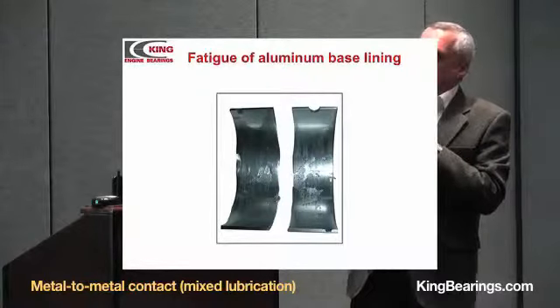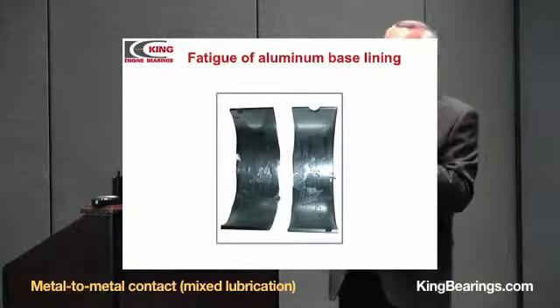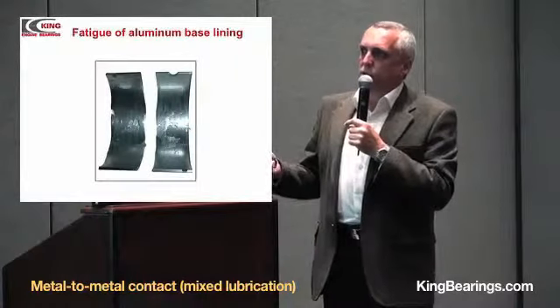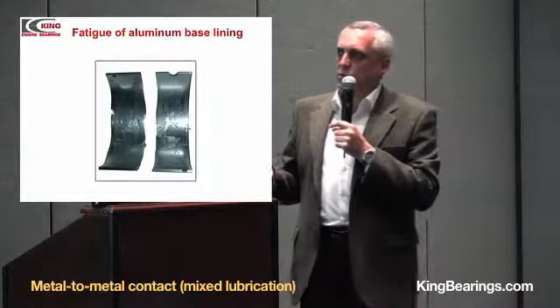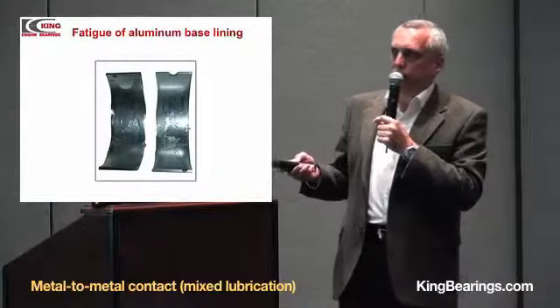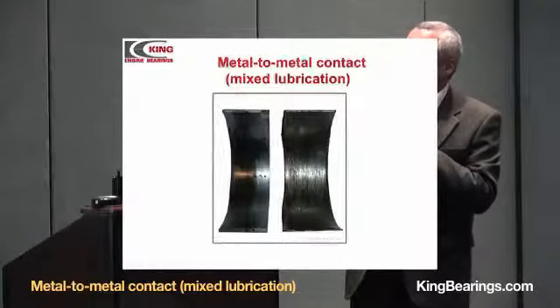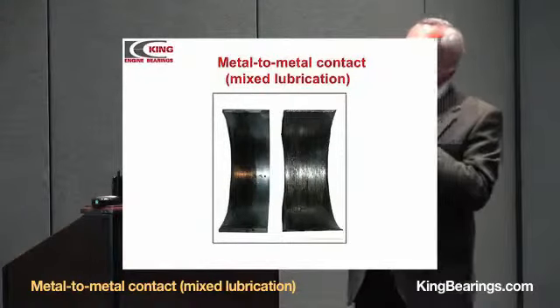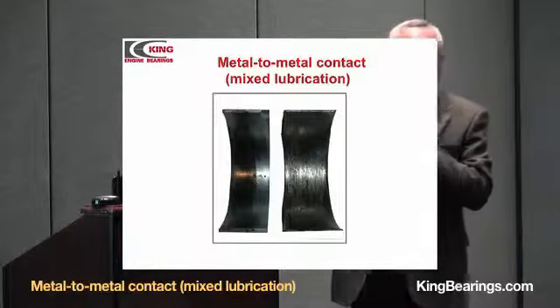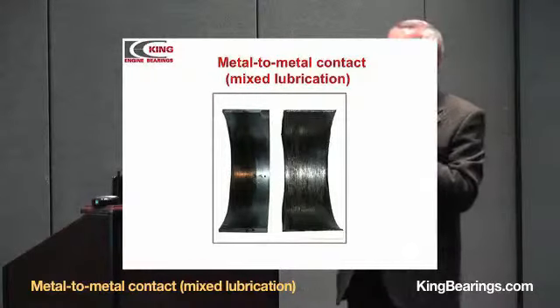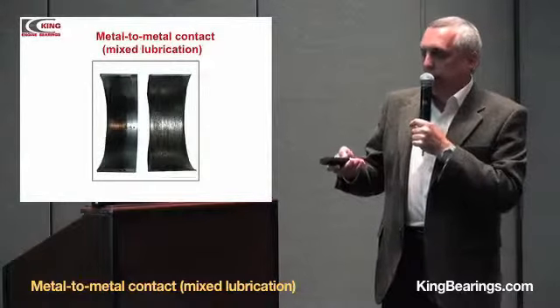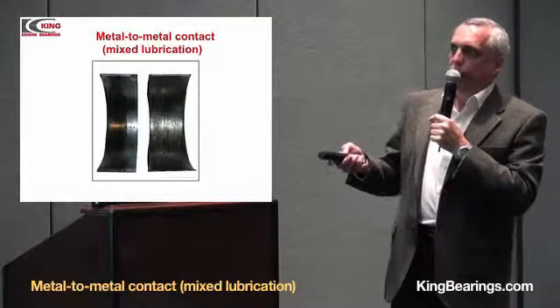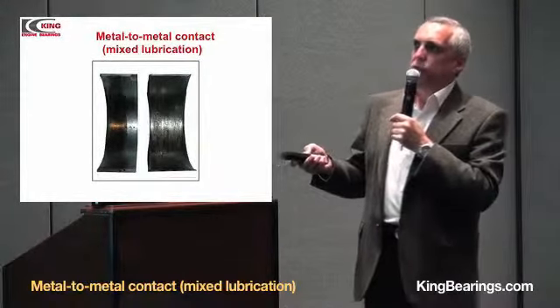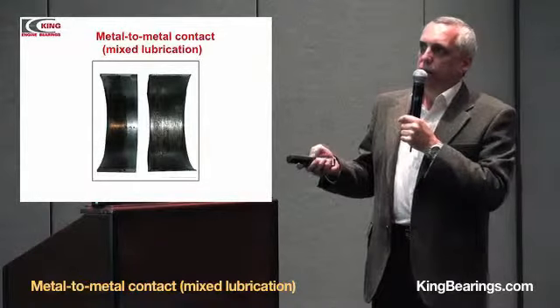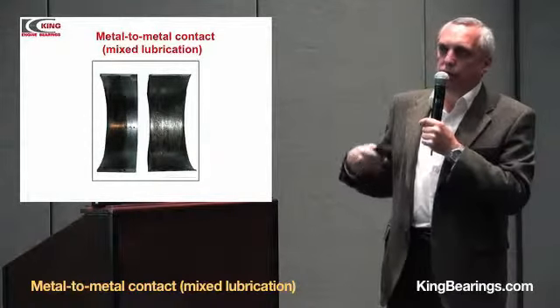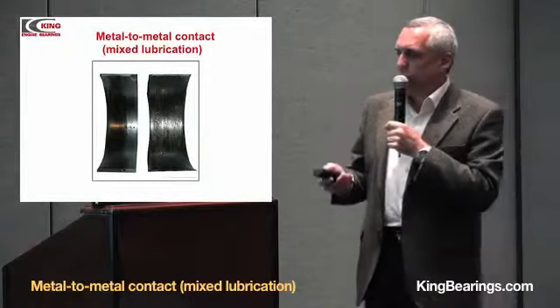You see heavily fatigued aluminum lining with parts of the lining delaminated from the surface, flaked off from the surface. Here you can see the metal-to-metal contact, mixed lubrication, or maybe even boundary lubrication. This is the initial stage of boundary lubrication, and this is the final stage. Here, overlay is gone, copper is gone, and steel is burned. So it's